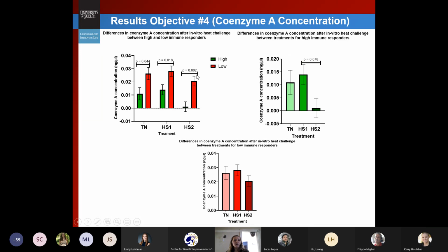And then this graph shows results for coenzyme A concentration, which is the output of the fatty acid oxidation cycle. So again, we're seeing our lows having significantly greater coenzyme A concentration across our 3 heat treatments compared to our highs. So that's the same pattern as what we saw for fatty acid concentration. And then when we look within phenotype across the treatments, we saw a trend towards our highs having a significant decrease in coenzyme A concentration from heat stress 1 to heat stress 2, whereas we didn't see any significant difference for the lows across the treatments.